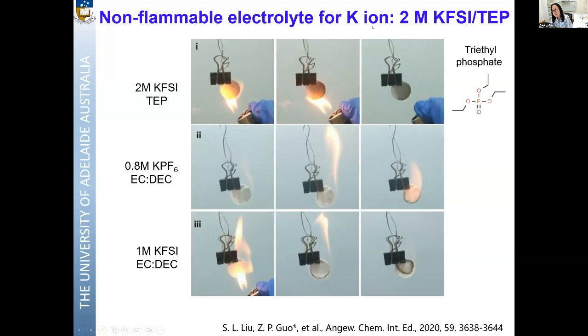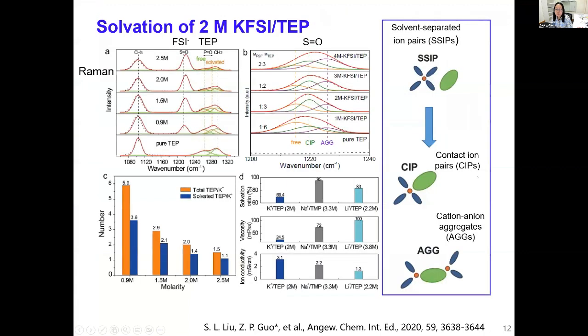In this case, for the potassium-ion battery, we employed fire retardant TEP as a single solvent. We use this solvent to dissolve FSI potassium salt, and we can develop a non-flammable electrolyte. We can see the electrolyte can't be ignited. When we remove the lighter away from this filter paper with the electrolyte, it can't be ignited anyway, suggesting it's not flammable.